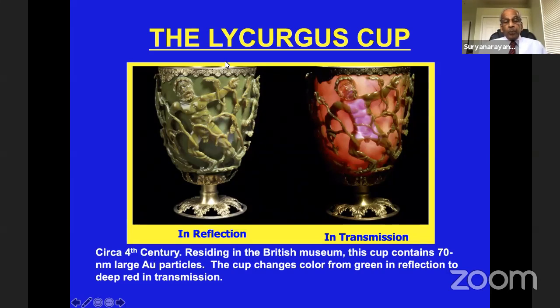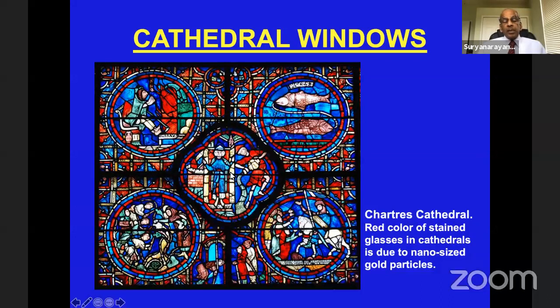Therefore, you can see, if you put a light outside this cup, that means in reflection, the glass color will be green. But if you put a light inside the cup, that means you look at the transmission, then it turns red. The reason appears to be that when you made these cups, there were very small gold particles, approximately 70 nanometers in size. And because of these small gold particles, the optical properties are different, both in reflection and in transmission. And you can also see these in cathedrals in most parts of the world. Again, this is because of the nano-sized gold particles present in the glasses that were produced for these applications.